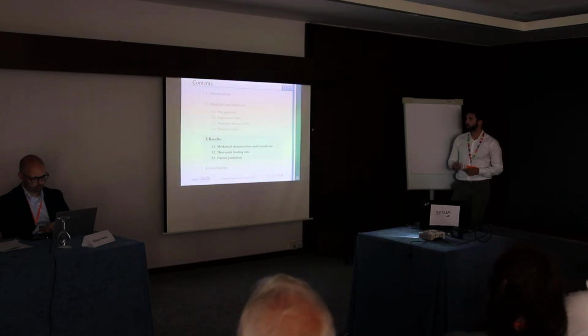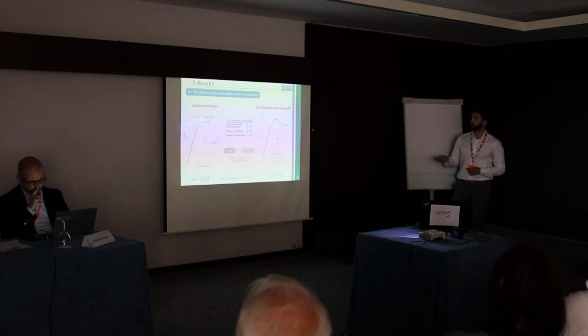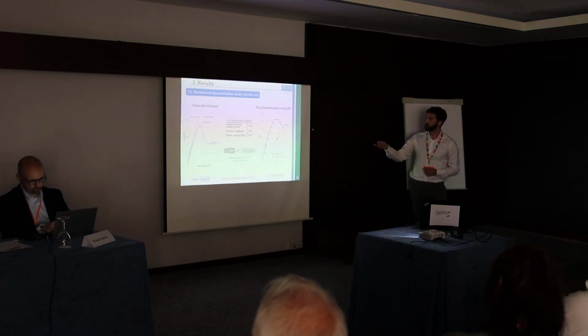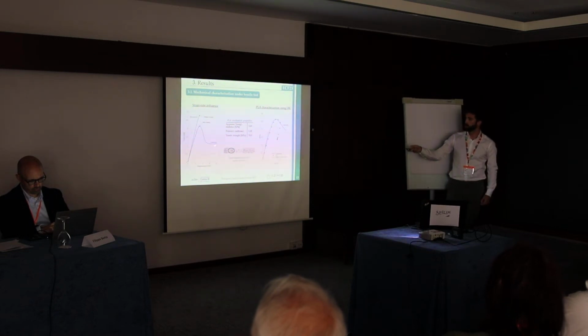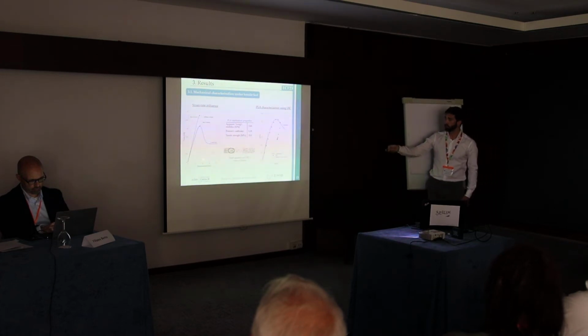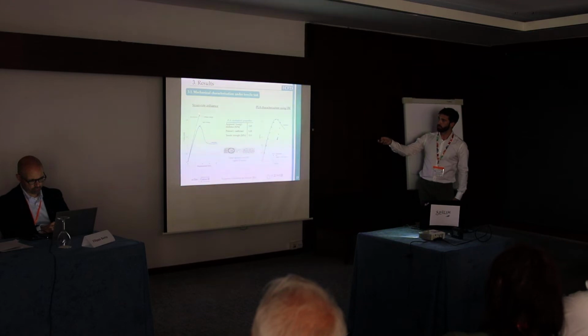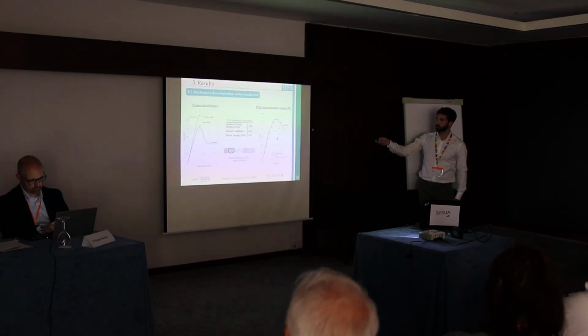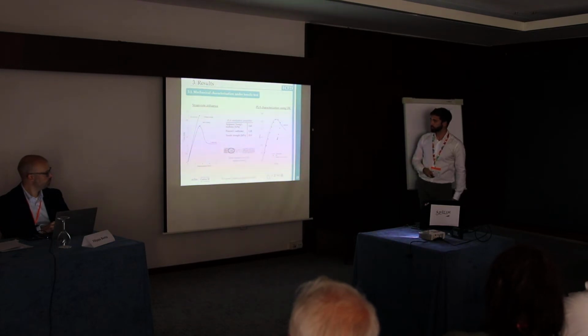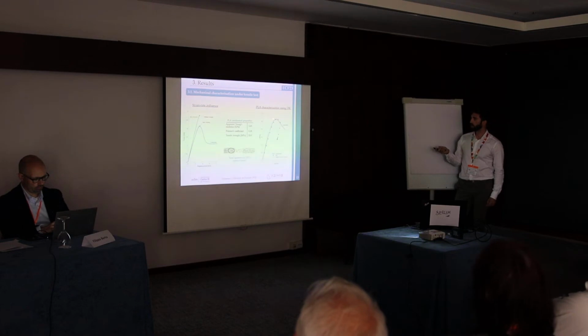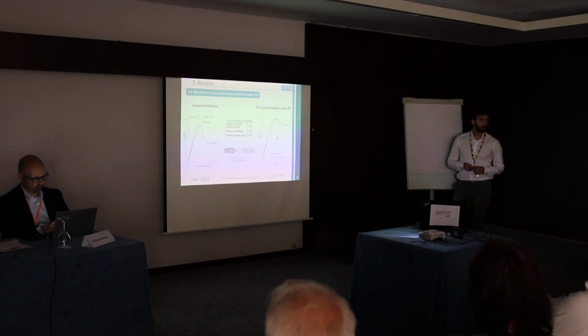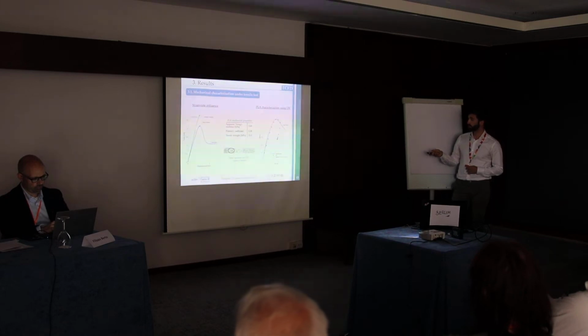Okay, so we can start with the results. Firstly, from the uniaxial tensile test for the characterization of the material. On the left, we have two force displacement curves for 1 and 50 mm/minute. You can see that while the 1 mm/minute reaches a stabilization zone with large displacement, when we increase the strain rate, the fracture is immediate, in very low displacement. And on the right, to calculate the Young's modulus and everything, we have the stress strain curve from the extensometer, and it helps us to validate the DIC response.